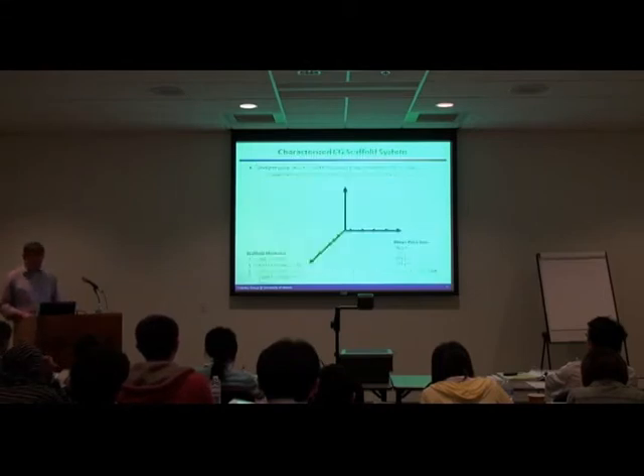But then when they turned around and came back the other direction, the cell would come to the membrane, make a decision, and not cross over onto the soft side, and would stay on the stiff side of the membrane. So what this is starting to suggest, and it's work that's been validated and built on in a number of different systems and a number of different cell types, is that there's a great deal to understand about the local mechanical properties, and as we're starting to look at local microstructural properties, how that affects cell behavior.